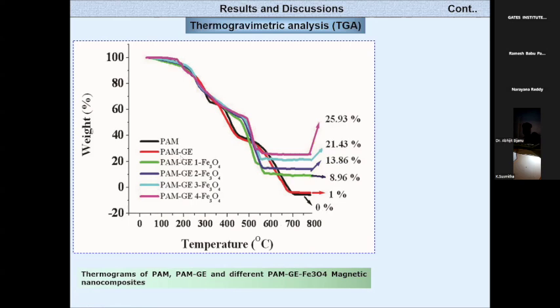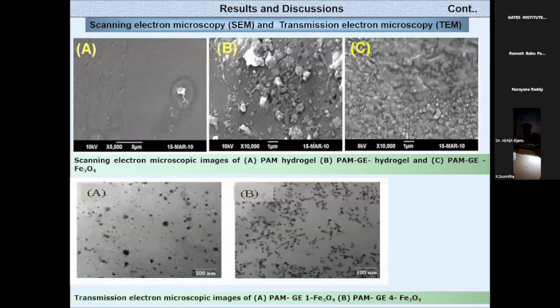Compared to PAM hydrogels, in PAM gelatin hydrogels, when you increase the gelatin content, the nanoparticle content increases. You can also see the morphology of the nanoparticles. When you see only PAM hydrogels, there is nothing, just a very uniform surface. With the PAM and gelatin hydrogels without iron, you also don't see any nanoparticles inside. But when you convert to the PAM and gelatin with nanoparticles, you see small areas with some nanoparticles, which confirms the nanoparticles inside your hydrogel network.